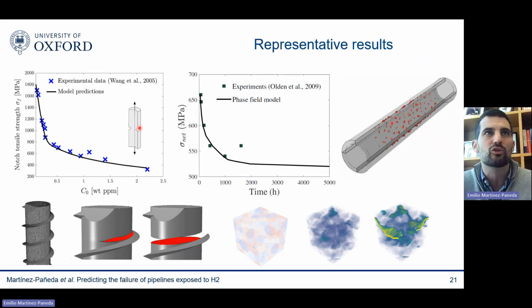These are pre-charged samples with notches. These are samples subjected to a constant load, where you can see that not only we get good agreement, but we can also run virtual experiments over very large timescales. And basically, you can do anything you want, right? So you can go down into the microstructure. You can see a polycrystal. We can resolve the microstructure and rank different polycrystalline microstructures and compare the susceptibility to hydrogen. These are cracks going through the microstructure. But you can also handle complex, large-scale problems. This is a classic screw failure test.